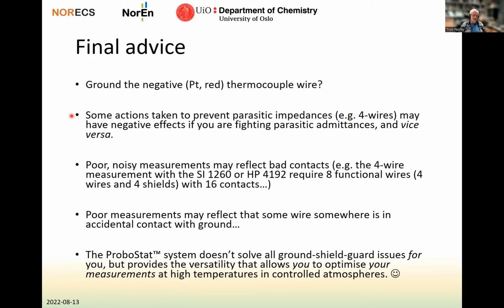Then you should be aware that some good actions you may take to prevent parasitic impedances, like using 4 wires, may have a negative effect if you are fighting parasitic admittances like cross conductance between wires, and vice versa. So that when you optimize for one thing, it may get worse for the other. So you should use a certain set of actions for high impedance samples and another set of actions for high admittance, high conductance samples.